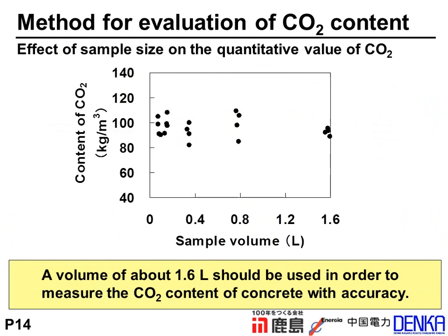This is a result of the correlation between the content of carbon dioxide in concrete and the sample volume. You can see that the value averaged around 100 kilograms CO2 per cubic meter, and as the sample volume increased to 1.6 liter, the fluctuation became small. So a volume of about 1.6 liter should be used in order to measure the carbon dioxide content of concrete with good accuracy.